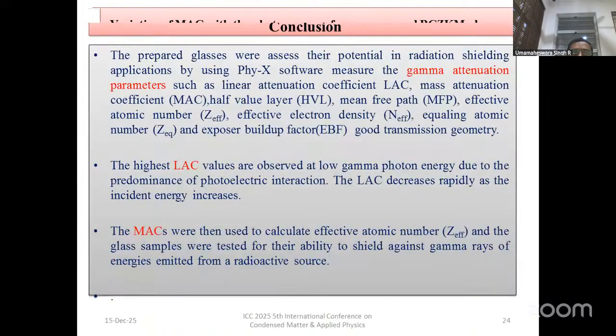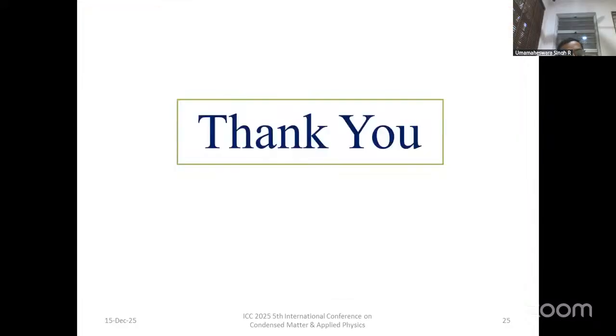Using this LAC and mass attenuation coefficient, other parameters can also be calculated, such as half value layer, mean free path, effective atomic number, and effective electron density. These are also very important in how the material shields the radiation. But majorly we have to determine LAC and MAC. The MoO3 doped potassium oxide doped borate glasses are shielding more effectively. That is the conclusion of my research.